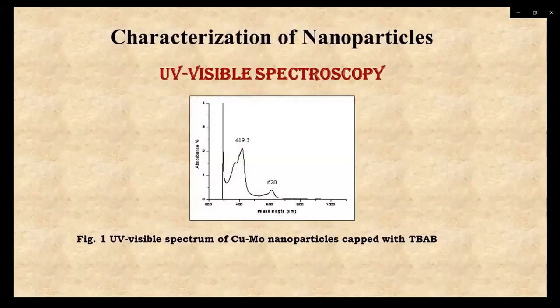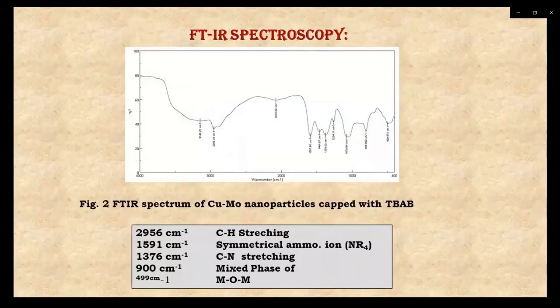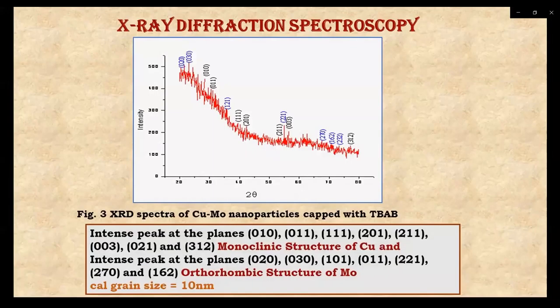These are the advantages of electrochemical reduction methods. This is the absorption spectra of copper molybdenum nanoparticles capped with tetrabutylammonium bromide. Here, the sharp peaks at 419.5 nanometer and 620 nanometer confirm the formation of copper and molybdenum nanoparticles. This is the FTIR spectra of copper molybdenum bimetallic nanoparticles. The spectrum between 400 to 900 centimeter inverse confirms the presence of copper molybdenum metals. In the XRD, the intense peaks and lattice parameter show monoclinic structure of copper and orthorhombic structure of molybdenum with particle size 10 nanometer, which is calculated by the Debye-Scherrer formula.